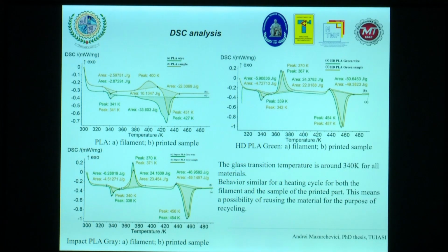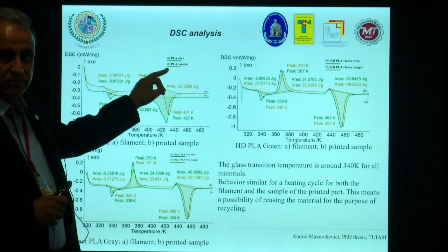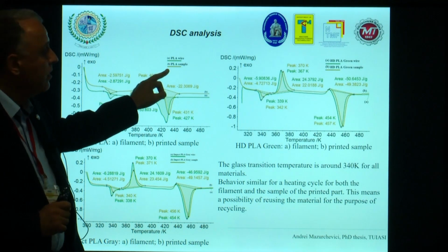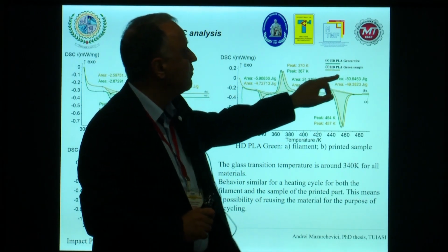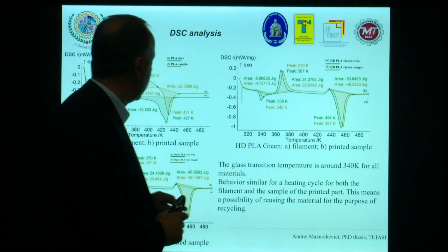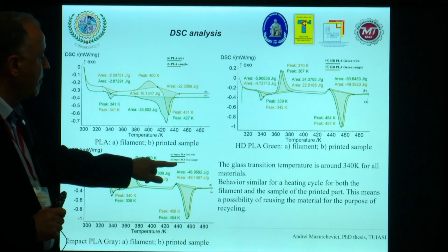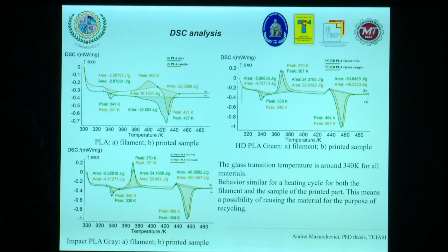You can see now the DSC analysis. We already made the DSC analysis for both, I mean for PLA filament and PLA sample, for all the materials. High density PLA green filament, high density PLA sample. Impact PLA gray filament, impact PLA gray sample, to compare the results between the filament and the sample.